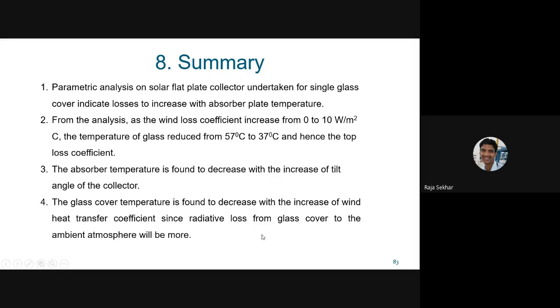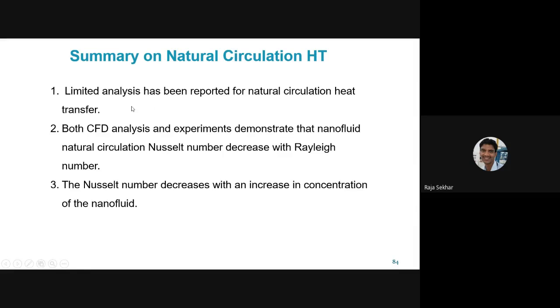So the glass cover temperature is observed to decrease with increase in the wind heat transfer coefficient, as it is obvious that the more the wind, the more the heat loss from the cover to ambient takes place. And there is a limited analysis reported on natural convection heat transfer with nanofluids. So there is a lot of scope for young people to do some more analysis on this natural convection heat transfer with nanofluids. Both CFD and experimental investigations demonstrate that nanofluid natural convection heat transfer will reduce the heat transfer rate with increase in the concentration of the nanofluid.